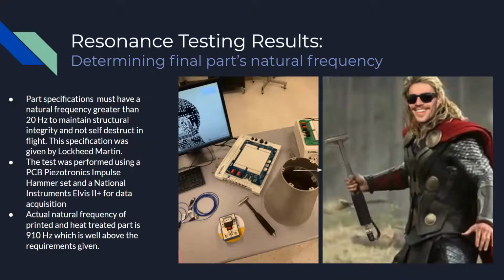Then a resonance test was performed to determine the frequency of the part. A specification of 20 Hertz was given to us by Lockheed Martin to ensure the part would not vibrate apart. The test was performed using a PCB Piezotronics impulse hammer connected to an NI ELVIS II board for the data acquisition. The part was then hit with the hammer, the frequency of the part was recorded, and data was compiled. The average resonating frequency through the part was around 910 Hertz, which is well above the given requirements.